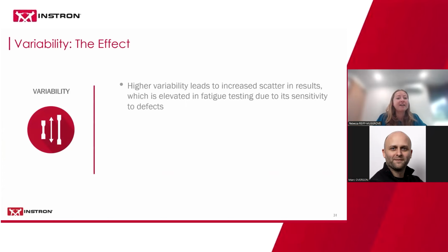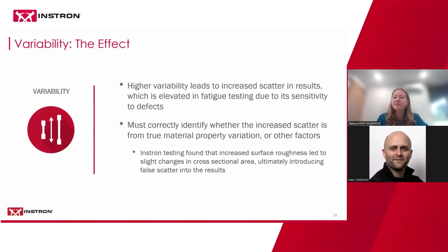And well, what is the effect of that? It might seem obvious. Higher variability leads to higher scatter in results. With fatigue testing, where they're even more sensitive to very small changes in defect density, etc., compared to tensile testing, you might get even more variation, as fatigue testing is so sensitive. And what this means is we also can't use that as an excuse. So if we see fatigue results that are very scattered from additive manufacturing, we also have to correctly identify whether that scatter is from that true material property variation or from other factors.